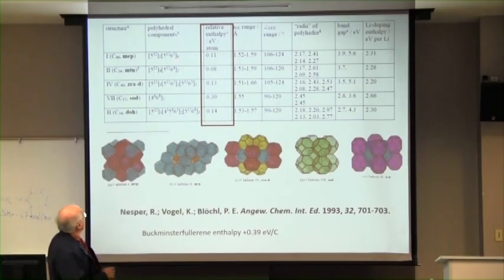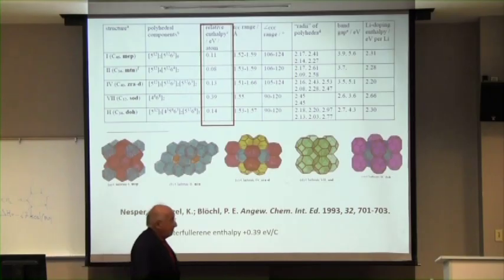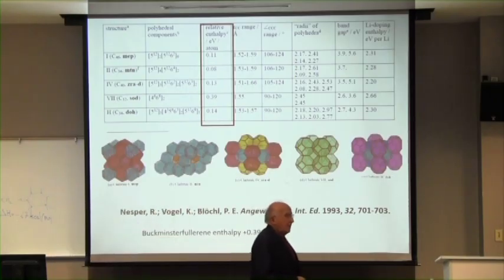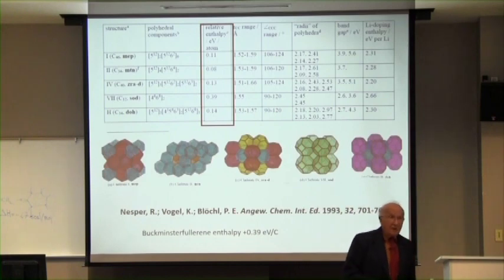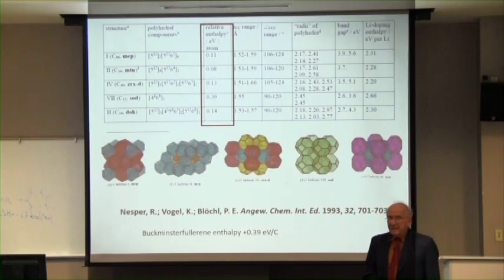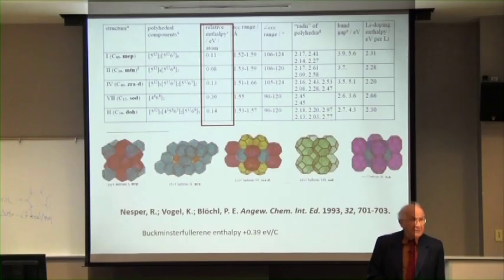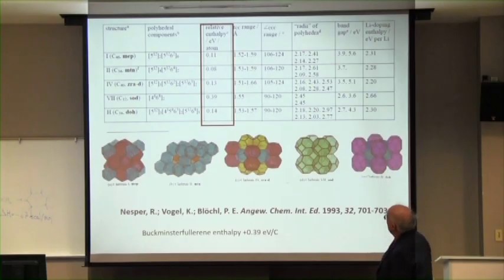But the best one, clathrate 2, is only 0.08 of an eV per carbon atom unstable relative to diamond. And once made, it's not going to rearrange to diamond any more than diamond rearranges to graphite once it's made, even though it's slightly thermodynamically unstable relative to graphite. Because you have to break bonds.